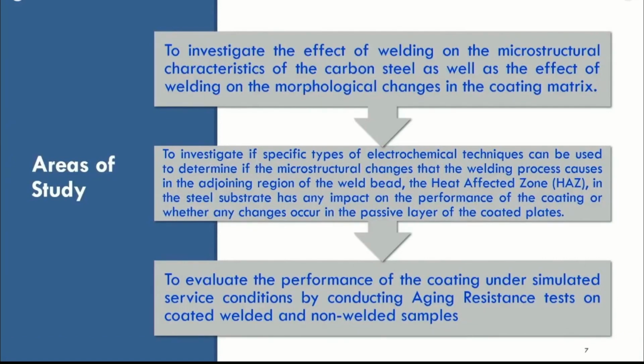We designed the test protocol to understand clearly what's going on during the welding and what's the effect of the welding on the microstructure of the steel and the morphology of the coating itself. Then we took it to the second stage. We tried to use electrochemistry, which is for the first time we're using it, to see what's the effect of this alloying layer formed during the welding and non-welding process comparatively. And the last thing, after we understand the system, we evaluated its performance under long-term immersion and cycling process, which simulate actual application in the field. I'm going to give you the result for each part, and then Benjamin from Chevron, the project leader for this, is going to wrap up the conclusion for you.